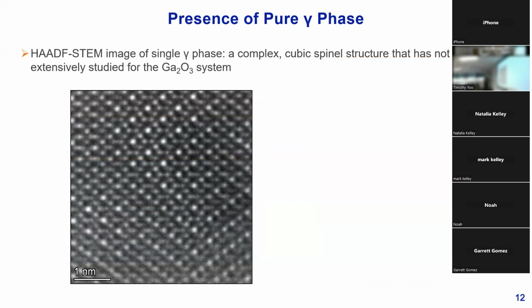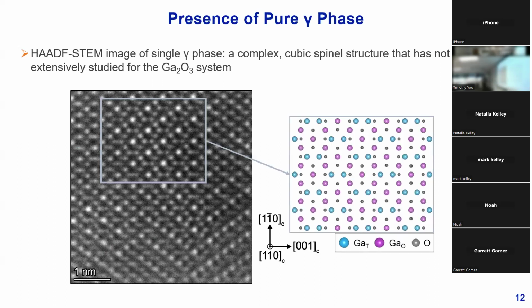And so getting right into it, in the as implanted film region, the first new finding we have is actually a confirmation of a phase transition, but now we see that it's actually to something called the gamma phase, not necessarily the kappa phase. And so this gamma phase is a complex cubic spinel structure. It's not really been extensively studied in gallium oxide, but we can see that by taking model structures from similar materials with the same space group, like magnetite, we can see that there's this nice pseudo-hexagonal motif in the dashed orange circle that's similar between both model and experimental images. So it gives us a pretty good idea of what we're looking at.